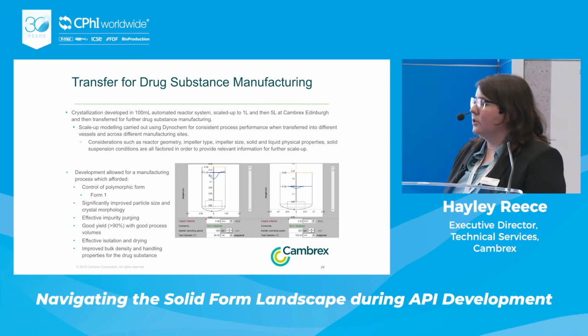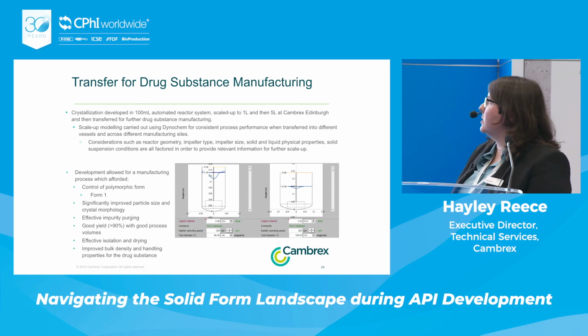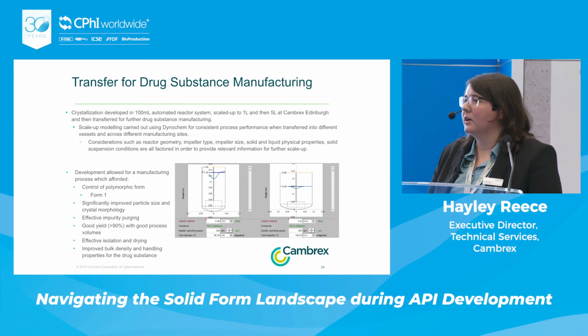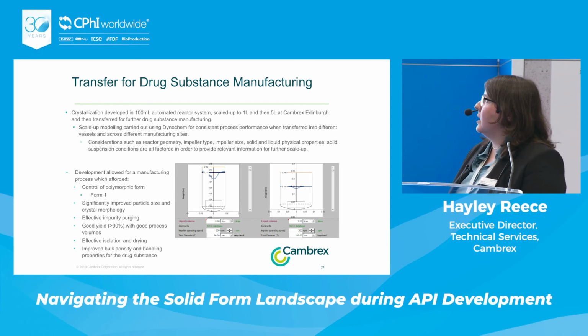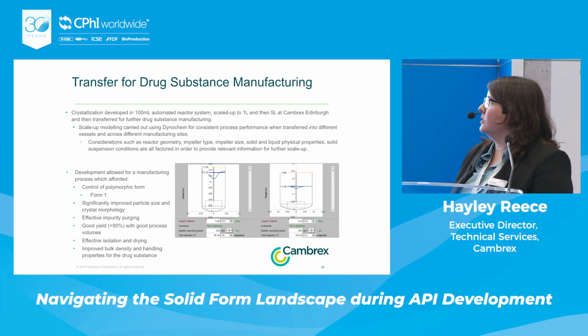So what we would normally do during these work programs, and what we did here for this case study, is go from 100 mL up to 1 liter initially, and then we took it up to 5 liters just to demonstrate that initial scalability for the process. And really the way that we do this is through Dynochem modeling. So we use this modeling software to be able to do a scale up and scale down model.